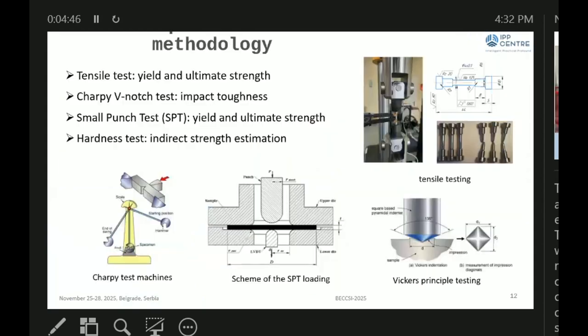To investigate thermal aging effects, 4 types of experiments were conducted. The first is the tensile test. For the tensile test, we designed and manufactured grips with adapters, which were mounted on our testing machine. This grip allowed us to conduct experiments at high as well as at low temperature. At least 3 specimens were tested for each temperature as well as for each type of material.